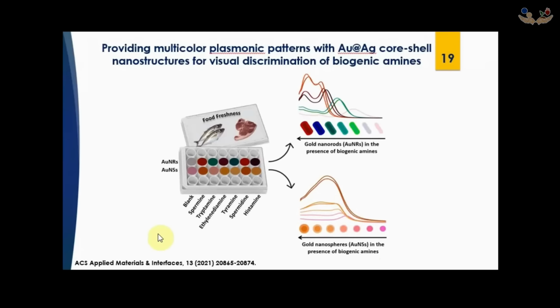As an example of the growth mechanism, we designed a multicolor sensor array consisting of two types of gold nanostructure, gold nanorods and gold nanospheres, for discrimination and determination of critical biogenic amines. Here are six biogenic amines: spermine, tryptamine, ethylenediamine, tyramine, spermidine, and histamine. The design principle of the probe was based on the metallization of silver ions on the surface of gold nanorods and gold nanospheres in the presence of biogenic amine.